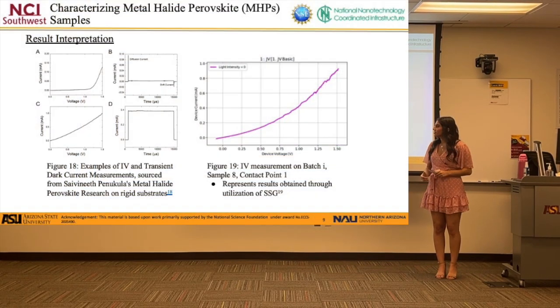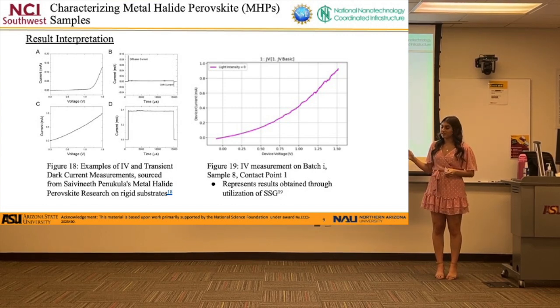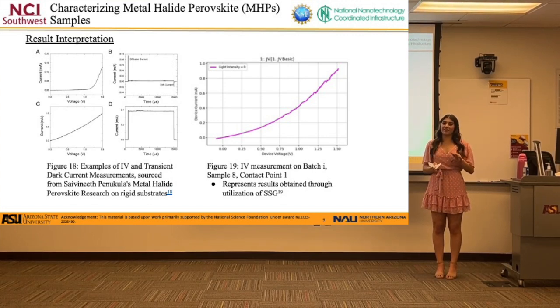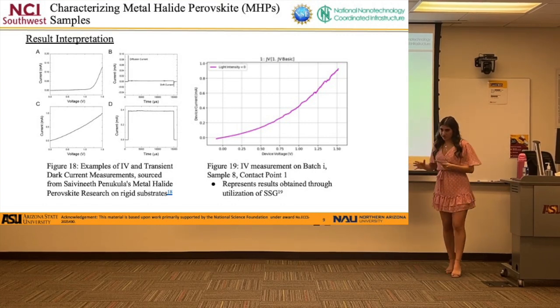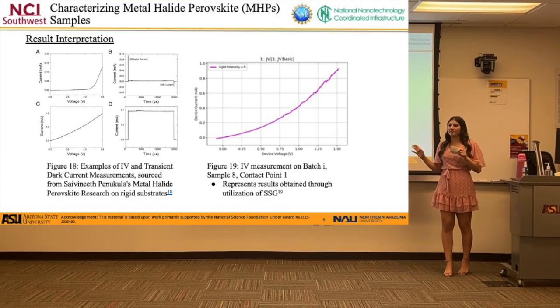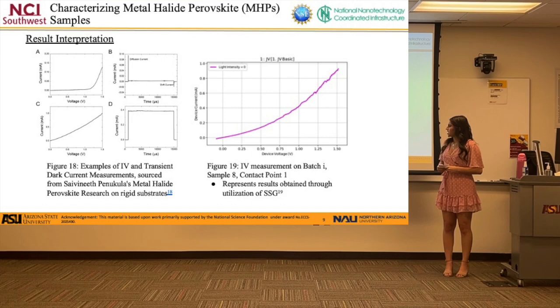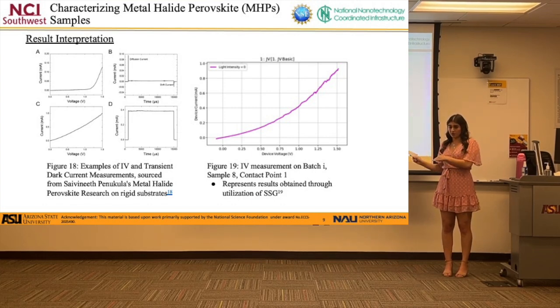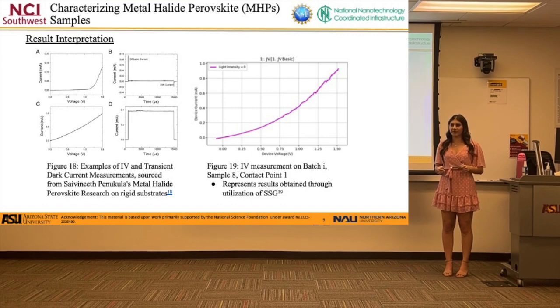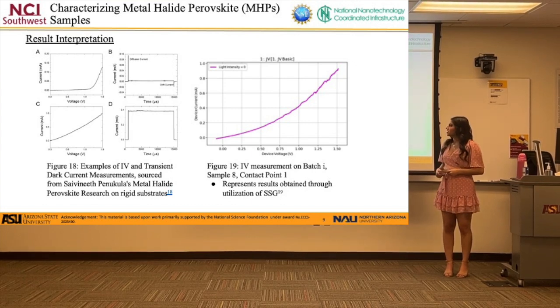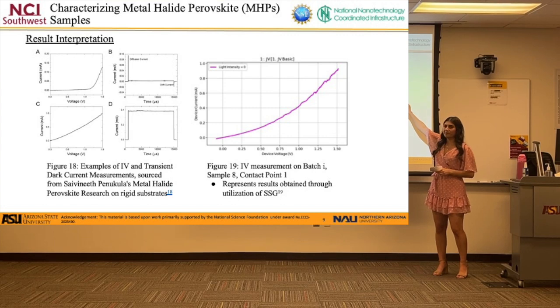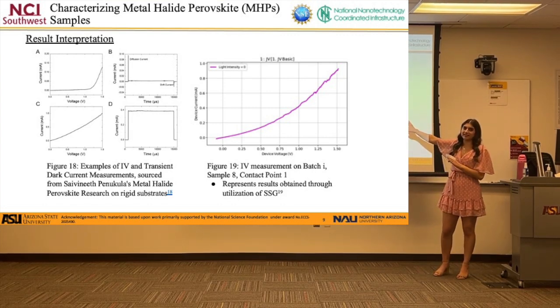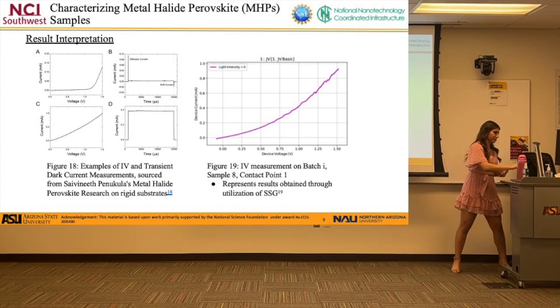C and D are not desirable examples because C demonstrates that this device is acting more as a resistor rather than a semiconductor, and D just demonstrates that this device does not have enough conductivity to produce an ionic drift current. So figure 19 was actually the most successful sample that I got, and this is important because this result was obtained through fabrication of the self-seeded growth process. Like I mentioned earlier, it was just depositing the perovskite twice in 2 separate spin cycles. So as you can see, it does have a little bit of a curve, but it is not quite at the point where it's acting like a semiconductor. At this point, it's more acting as a resistor.